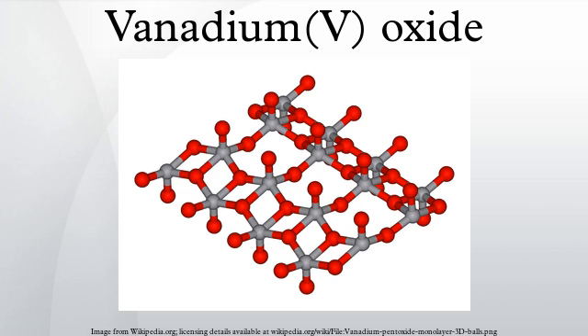Ferrovanadium production: In terms of quantity, the dominant use for vanadium oxide is in the production of ferrovanadium. The oxide is heated with scrap iron and ferrosilicon, with lime added to form a calcium silicate slag. Aluminum may also be used, producing the iron-vanadium alloy along with alumina as a byproduct.